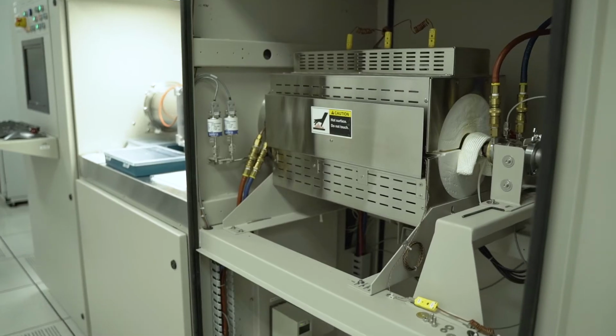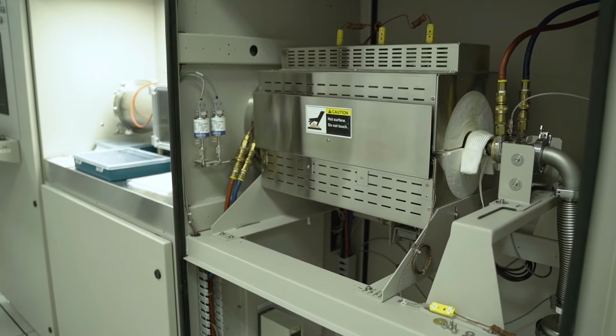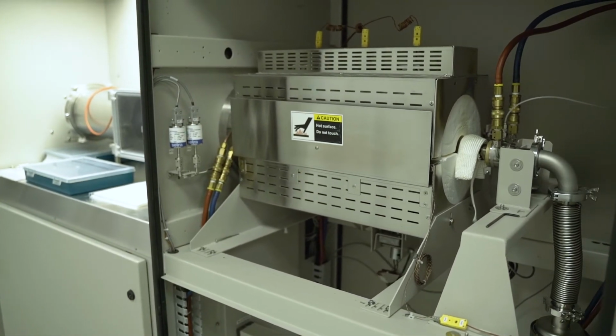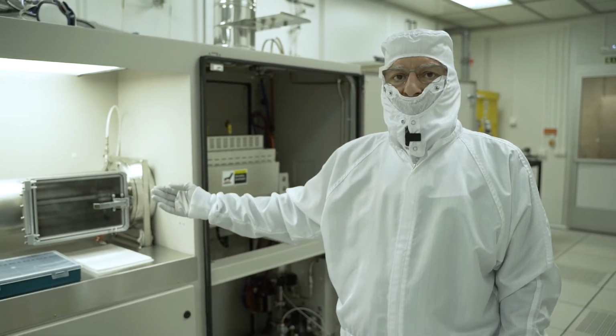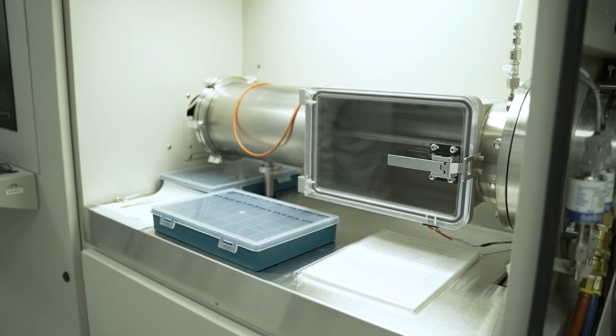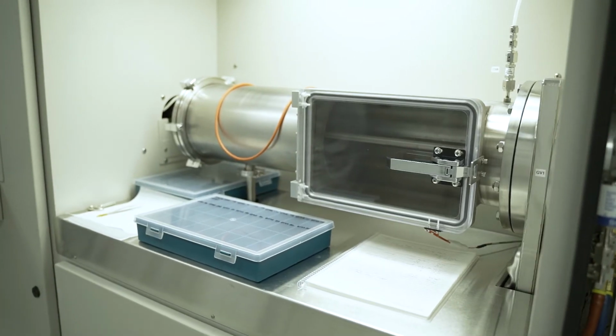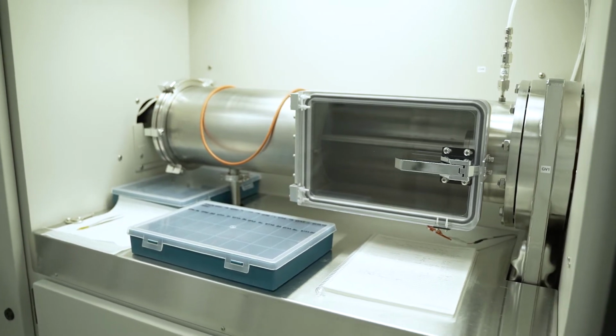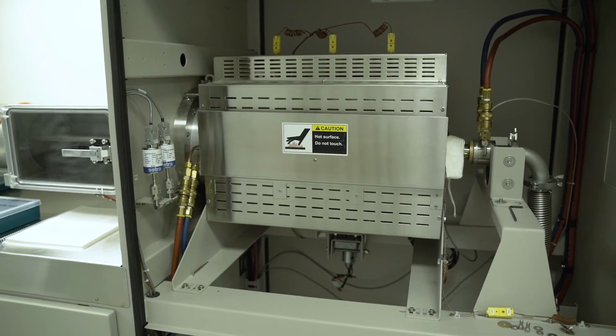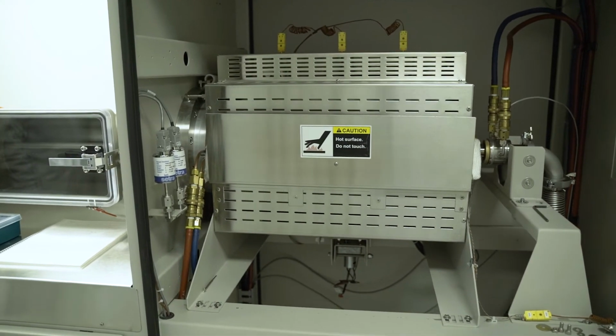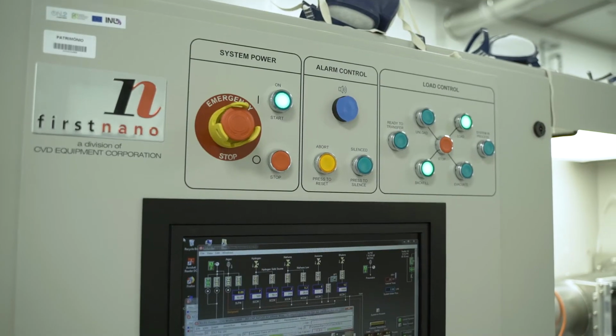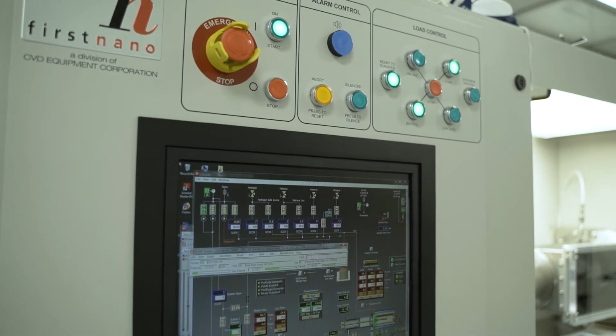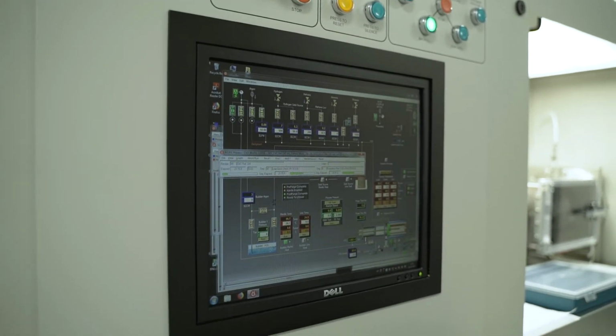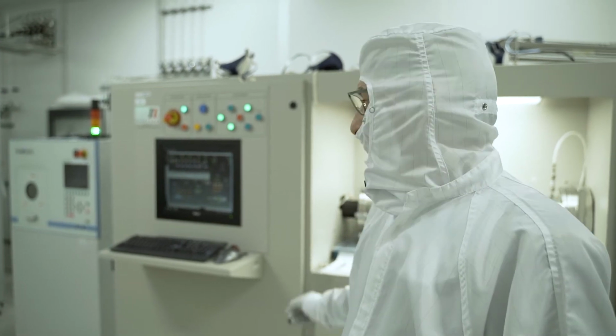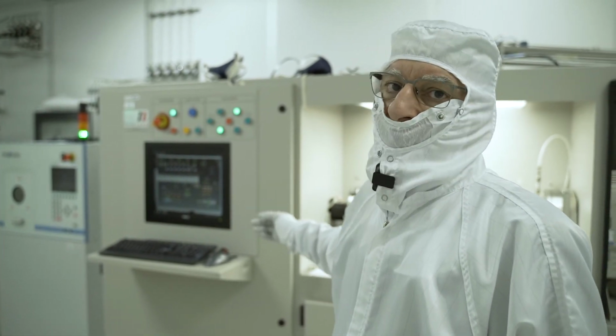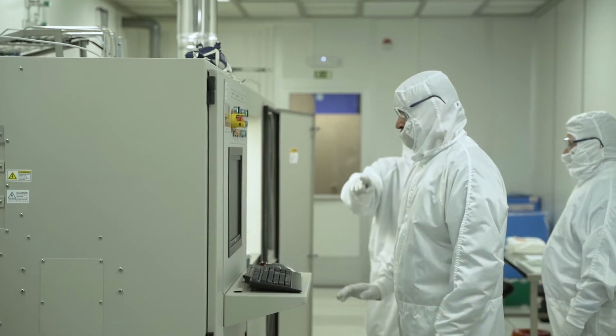This is the system for chemical vapor deposition of our graphene samples. It is a hot wall furnace, which is in this compartment. Here you can see the load lock, where we load the sample in order to avoid contamination of the main reactor. And here you have a graphical user interface where we can control and choose all the parameters of the deposition, and we can also monitor everything that is going on inside the reactor.